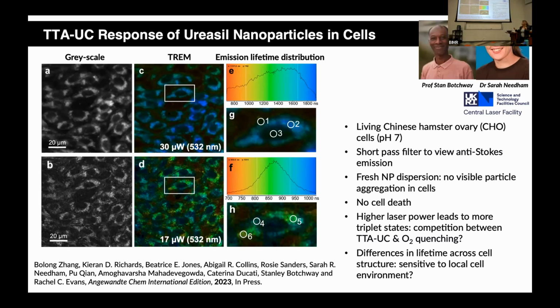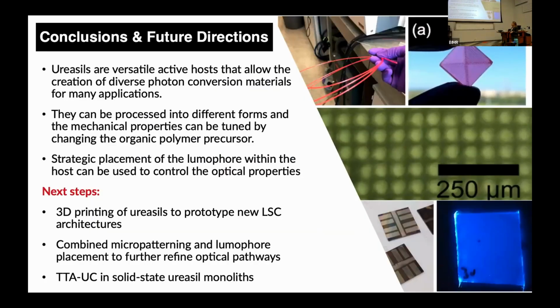But interestingly, this varies across the cell structure. So depending on where the nanoparticles are localized, we get more or less sensitivity to oxygen. And so this is where we had not expected that at all. So this is now where we're starting to look to see, can these actually be sensors as well because of the oxygen sensitivity across the cell structure? Will it also be diffusion dependent, for example? Can we get an idea of changes in microviscosity in the cells? And so on. So with that, then I'd just like to conclude.